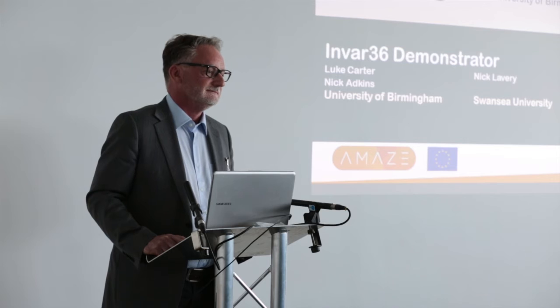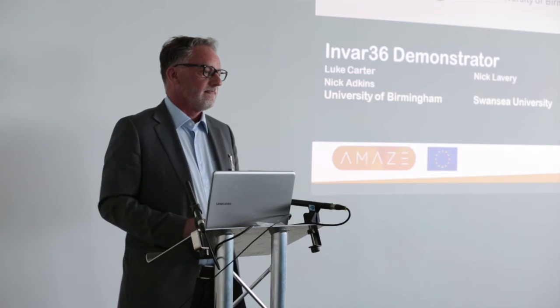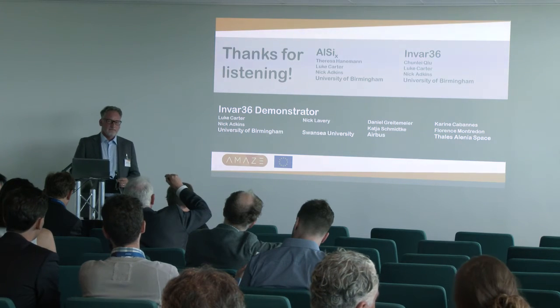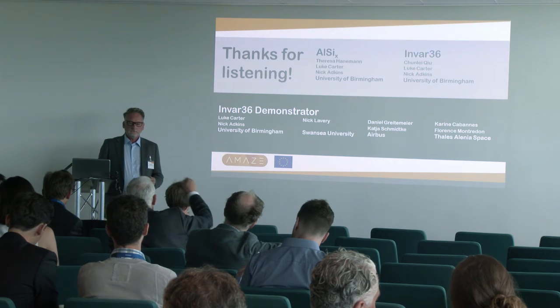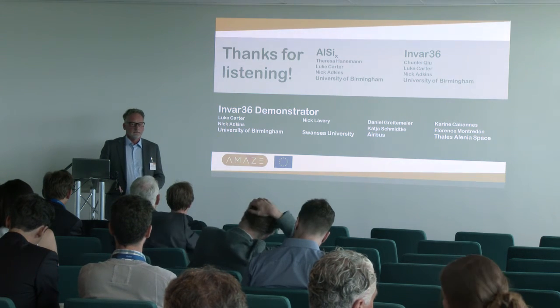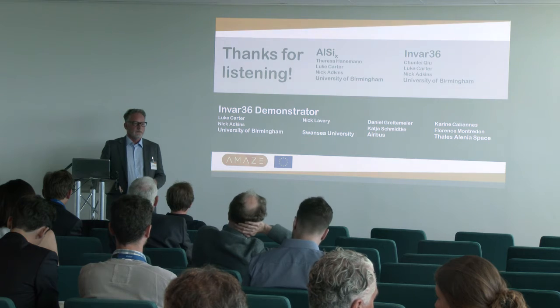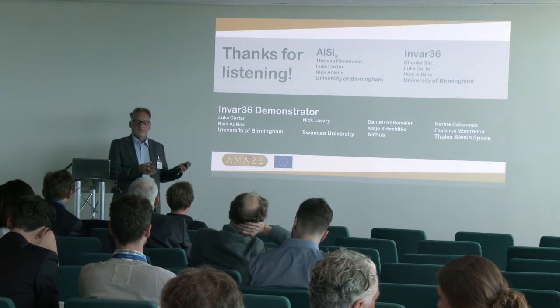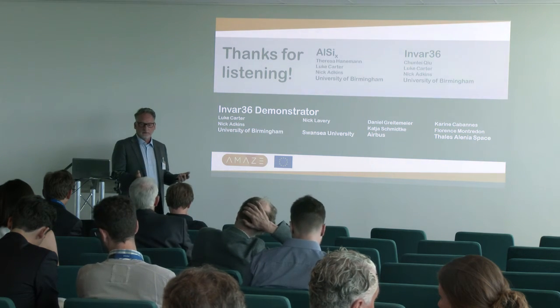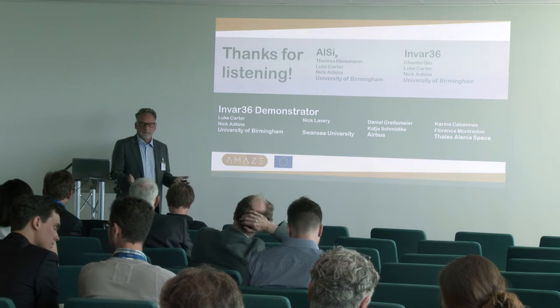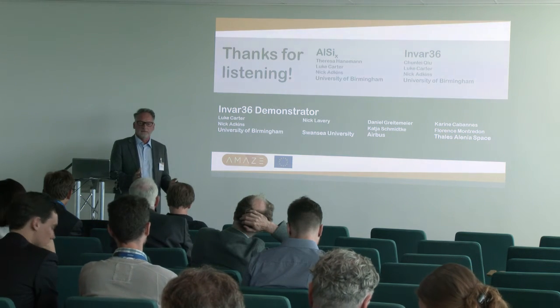Hello. Just a quick one on the aluminium silicon. Was that mechanically alloyed, or was it melted? The silicon added into the melt and then atomized? So the silicon was put into the melt for the 6061 material. So it's a proper melt, and it's atomized, and then they took out the fraction that we needed from that.